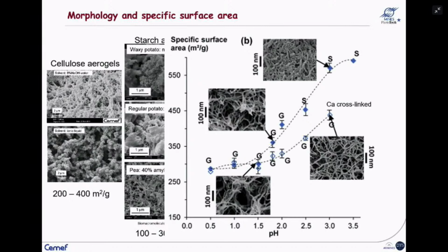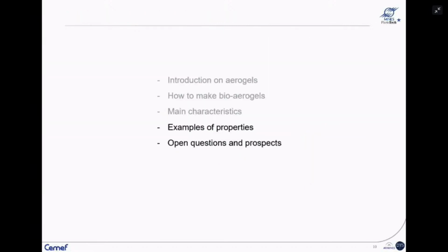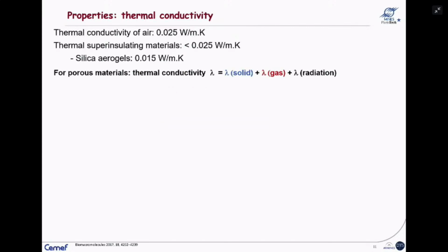So you can tune the morphology and the specific surface area by changing the starting conditions of your solution, and it can vary a lot. Still, specific surface area is very high, from 300 to almost 600 square meter per gram, but okay, you can play with this depending on the application you want to use for your bioaerogels. So these were the main characteristics, and then a few examples of the properties.